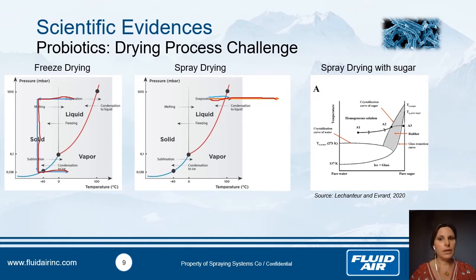So it's really interesting. To optimize the process for freeze drying and spray drying, most of the time it's interesting to use protective agents. Most of the time we use sugar. The one most used, and that we will use in this study, is trehalose. In this case, we just have to be careful when we use spray drying not to be in a glass transition phase, so as not to have something like a rubber in the tower, which is very difficult to dry, and you don't obtain powder, you just have something like a chewing gum. That is also interesting with trehalose, and we'll come back to that: it stabilizes membranes and proteins by replacing the water around polar residues within the macromolecular structure. So we will come back to this point.